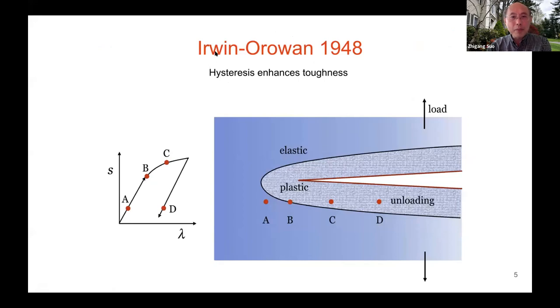That's not the field of action. The field of action for many decades has been an elaboration of this insight from Irwin and Orowan, two papers published in 1948. The insight is summarized in a single sentence: plasticity enhances toughness. Here's a stress-strain curve. When you apply a force you have displacement, and it's nonlinear. When you unload, reducing the force, the loading curve and unloading curve are separated, and this is the work or energy dissipated.